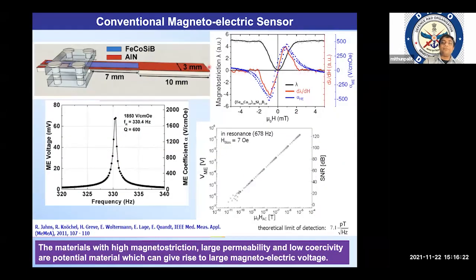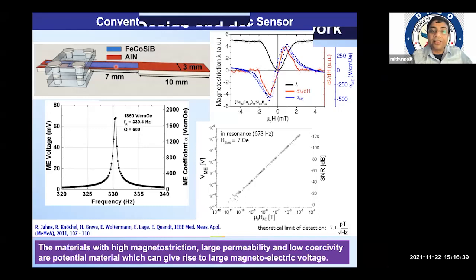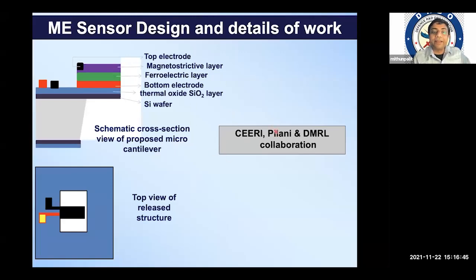And then conventional magnetoelectric materials are made with iron, cobalt, silicon, boron amorphous material as the ferromagnetic layer, and aluminum nitride as the piezo layer. And the performance of this material is not so good like the magnetostrictive and the piezo combination. So accordingly, we have collaborated with IIT Pilani for fabrication of the devices. And you can see over here, this is the top electrode. Beneath, we have a magnetostrictive layer, and below we have a ferroelectric layer, and then there is a thermally grown silicon oxide, followed by the silicon wafer.